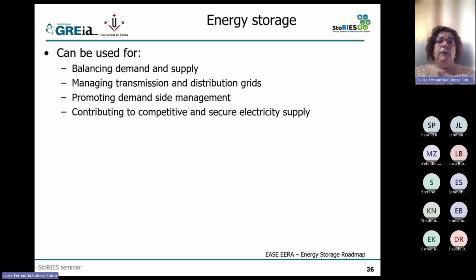You need probably a heat pump to increase the temperature of your energy, but with the storage, all of this system works better. You can also balance in power, as we already said. I have the energy at very low power, so I charge slowly. And then I need a big power, so I discharge fast, okay? And the last way of balancing is by location, okay? I can have the energy here. I can transport the energy to another location. You can do that with a heat transfer fluid, but you can do that also with the storage. For example, charging a store. It can be a water store, difficult to transport. It can be a PCM store. It can be a thermochemical, for example, with zeolites. And I put it in a lorry and I transport it to another place where I use the energy.